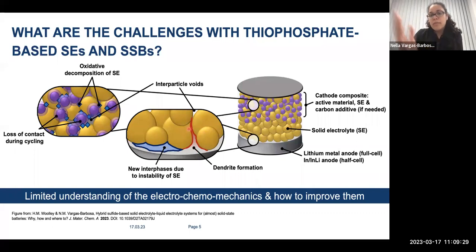There's also the challenge of dendrite formation when using lithium metal as a target anode—this is not a solved problem. Dendrites can grow along grain boundaries and have been shown to puncture solid electrolyte particles. Additionally, when you zoom in on a solid-state battery, you see interparticle voids that act like air bubbles, leading to very high resistances. Liquid electrolytes don't have this problem because they conform to everything. Solid-state batteries therefore tend to require significant applied pressures to run and keep running.